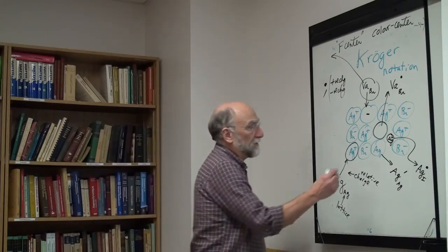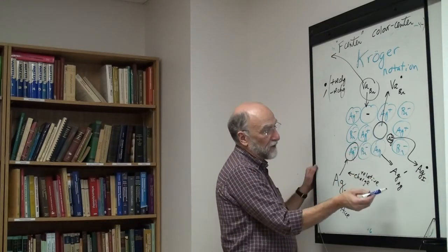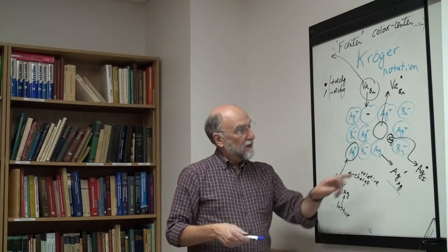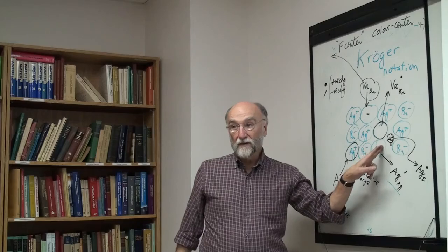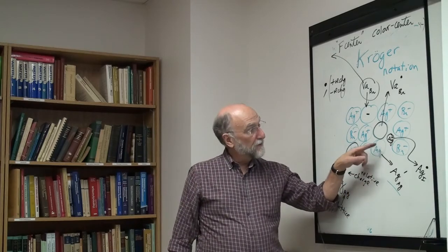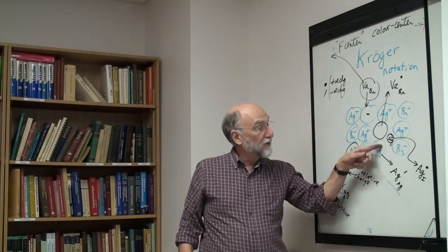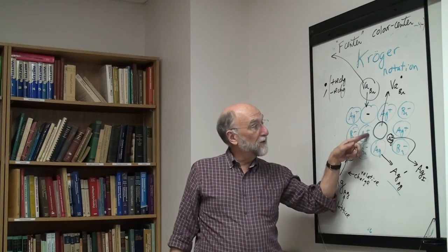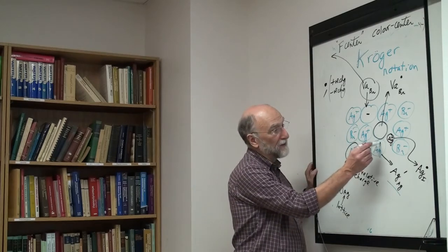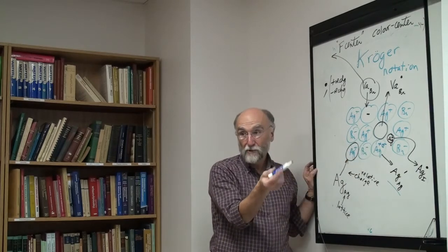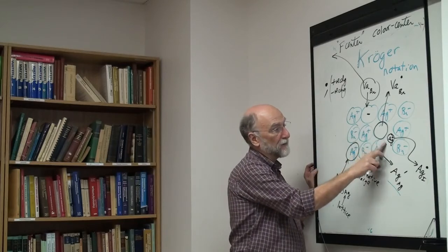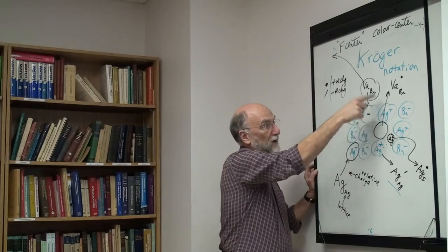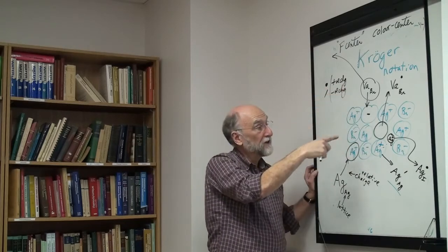What is this silver atom? The other way to look at this kind of defect, which is a silver atom on the silver site, is that this is an electron in the conduction band. Because really this is a silver ion which has an extra electron. There's an extra electron here that shouldn't be there. That electron can very easily hop to the neighboring silver. So this is like a silver ion with an electron, so it's a neutral silver. This electron can hop over to here. This then becomes a neutral atom, and the electron can hop from silver to silver very easily.